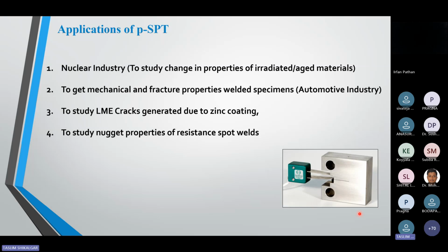Major application of this PSPT specimen in the nuclear industry is to study the change in the properties of the irradiated or aged materials. Second major application of the PSPT is to get the mechanical as well as fracture properties of the welded specimen. That is the upcoming trend. So people want to find out the properties of the welded specimens. Suppose they are making two halves and welding them, and they want to find out how much fracture property they are getting from this weld. So this is the upcoming phenomenon.